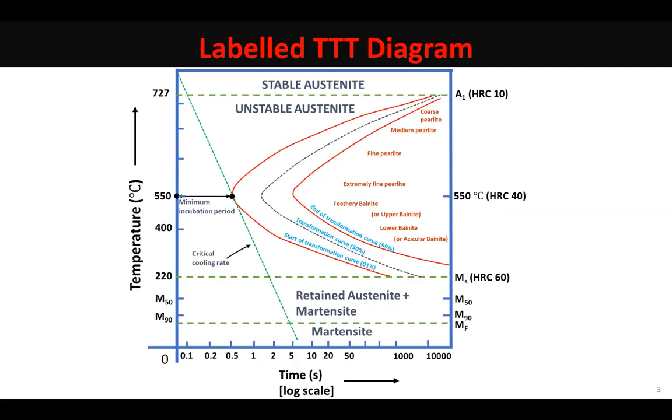And mind it, gamma iron has about 100 times more solubility for carbon as compared to alpha iron. So you had taken austenite, and there was a good amount of carbon present in that austenite. For example, we are talking about this 0.77% carbon steel. Gamma iron's maximum solid solubility for carbon is 2.11.